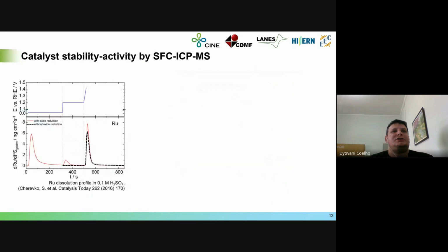And here I show you an example of this, where they did a study of benchmark catalysts for the oxygen evolution reaction in acidic medium and in alkaline medium. The example that I'm showing is ruthenium, where we can first see the contact peak dissolution. This one is just the contact of the electrolyte with the catalyst surface. So when the scanning flow cell is in contact with the catalyst, we can see a high dissolution of the ruthenium that stabilizes with time.